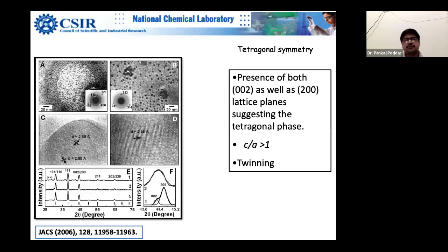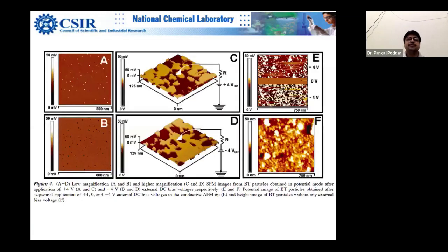So how is this green chemistry method able to stabilize the tetragonal phase, which is not so easy by other methods? The key lies in the surface. As I mentioned, it was predicted in a theoretical paper using DFT calculations that the crystalline phase you get is controlled a lot by surface chemistry. Here, the surface is covered by all these biomolecules, which are somehow responsible for stabilizing the bulk symmetry even at nano size. The mechanism is very difficult to predict, but this is what is happening.